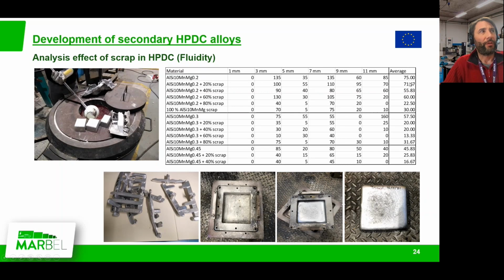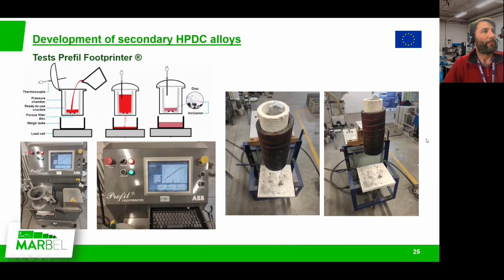Okay, you can see here that by increasing the scrap from zero we have about 75 as the value of fluidity. Let's say that it's an average length of this mold here, the different strips of this mold. We are decreasing to 22, 30 with 80%, 100% of scrap. The same for different alloy compositions, we are decreasing quite a lot the fluidity of the alloy by increasing the rate of scrap. And this is due to the presence of non-metallic inclusions that, due to contamination, are present in the scrap.